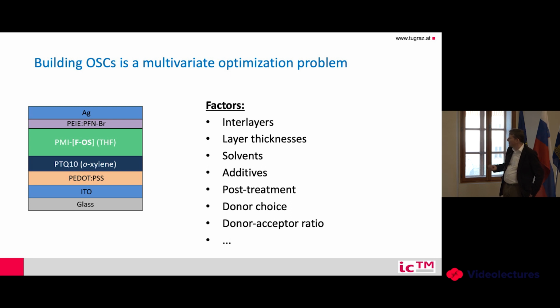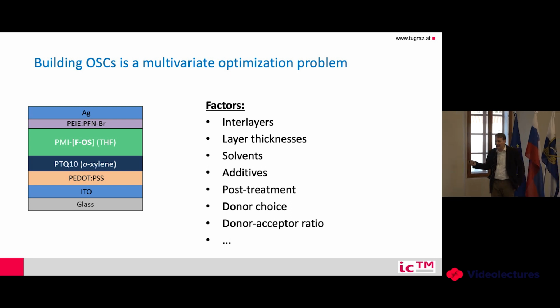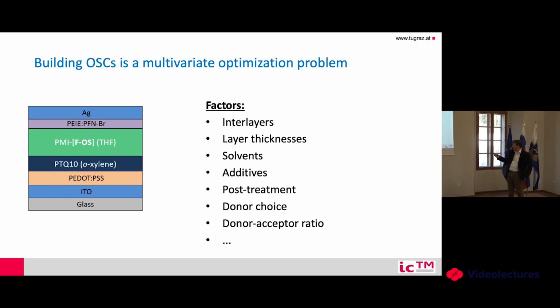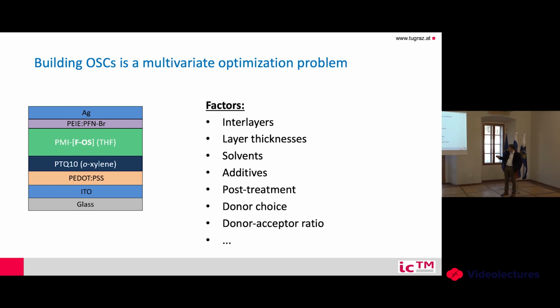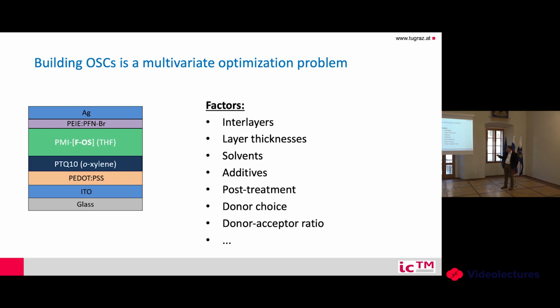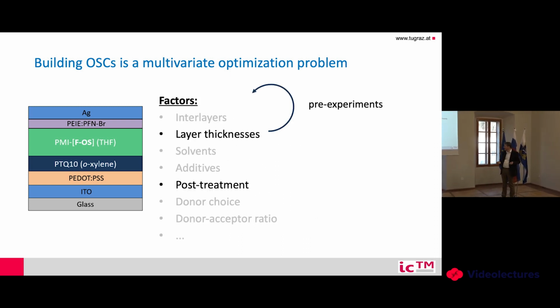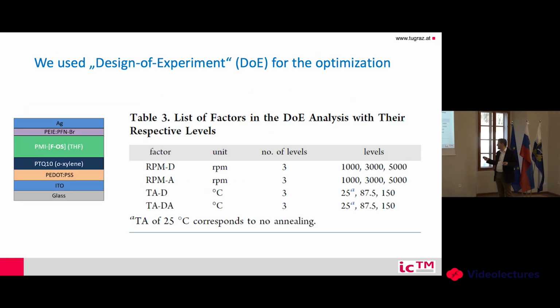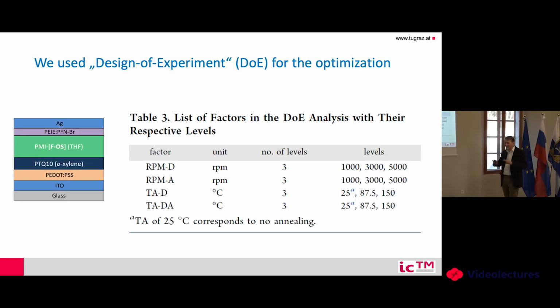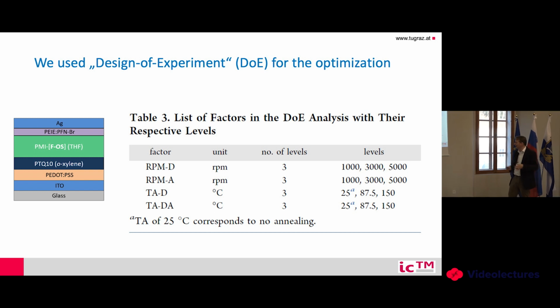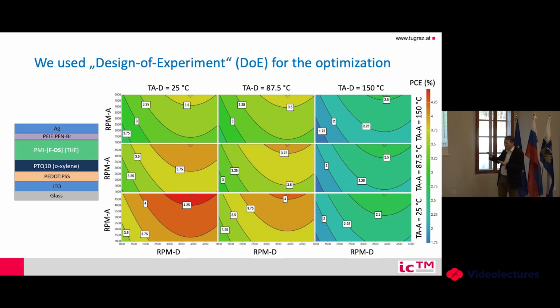Yeah, so actually you have a lot of different factors which can influence your performance. So you have, of course, every layer, the layer thickness, the solvent, there is some post-treatment, the ratio between these two materials. So you have a lot of different parameters, and in this case, we tried to do it by a design of experiment study. So we set some statistical parameters and really tried to find the optimum, varying this, finding the optimum parameters. Actually, it worked quite fine.